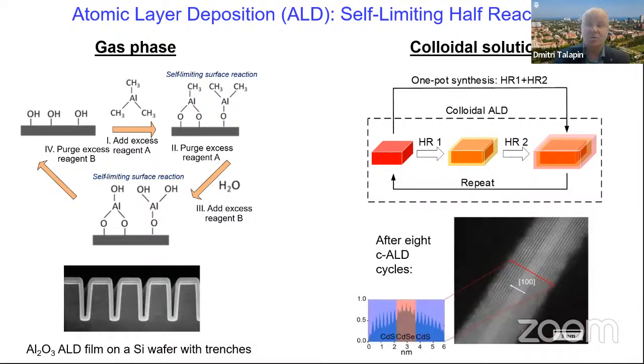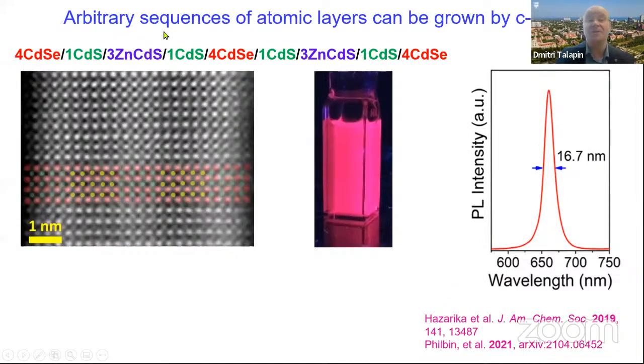And that allows you to grow semiconductor heterostructures, starting with our atomically precise substrates, and then add one layer at a time, an atomic layer at a time, and grow nearly arbitrary sequences of atomic layers in solution. And, for example, synthesize epitaxial stacks of multiple quantum wells separated by barriers that are also engineered with close to atomic precision, or more accurately, atomic layer precision.